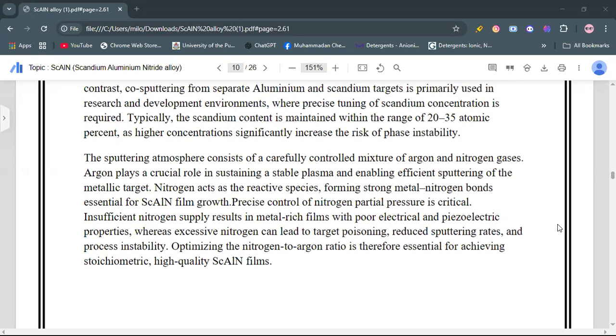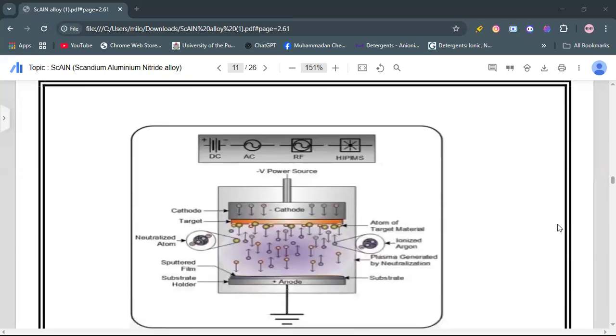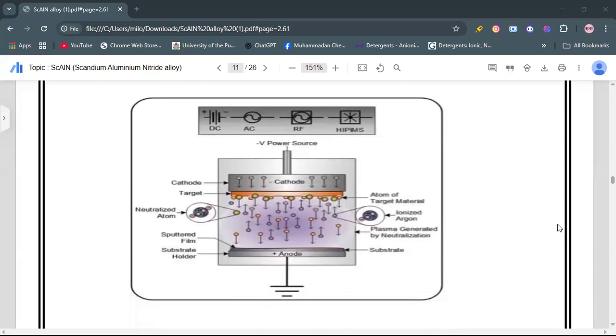Precise control of nitrogen partial pressure is critical. Insufficient nitrogen supply results in metal-rich films with poor electrical and piezoelectric properties, whereas excessive nitrogen can lead to target poisoning, reduced sputtering rates, and process instability. Optimizing the nitrogen to argon ratio is therefore essential for achieving stoichiometric, high-quality scandium aluminum nitride films. This is the diagram.